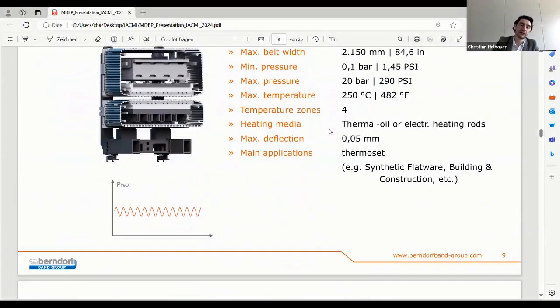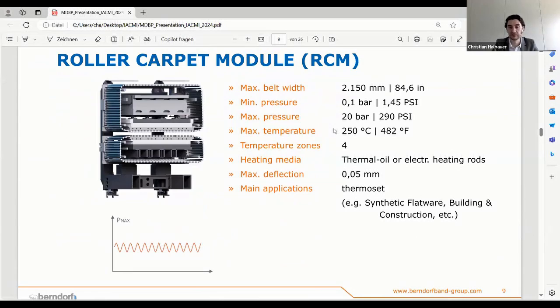So this is our model for the composites that are based on a thermoset production procedure. This is the one we would use. We can go up to a width of 2.15 meters, which is around 85 inches. And we have the possibility to integrate different temperature zones within the roller carpet module. So if, for example, the overall length is 8 meters, we can divide this into 4 sections, each around 2 meters, for achieving a consistent or, if you want, an increasing temperature curve, whatever you need for your product.